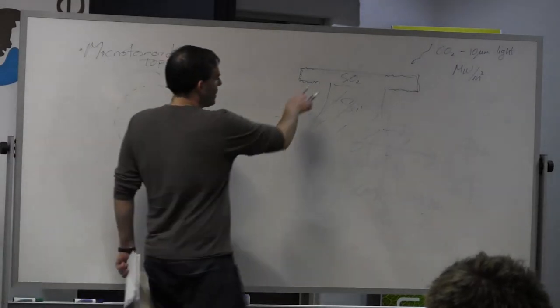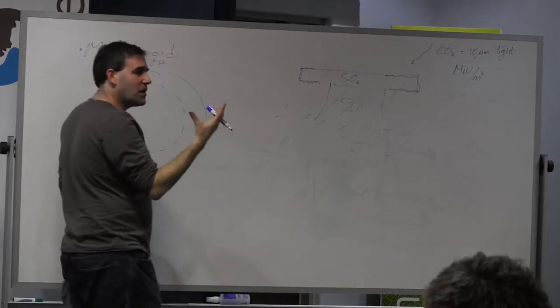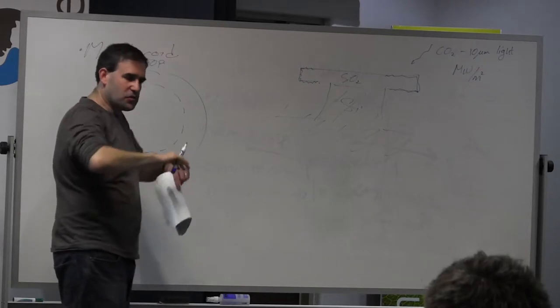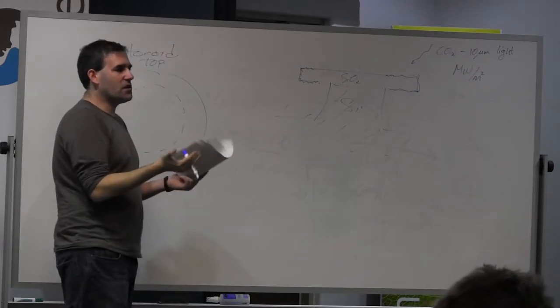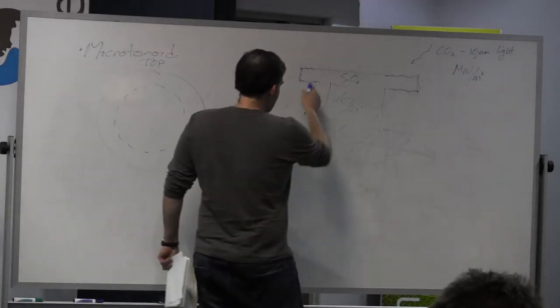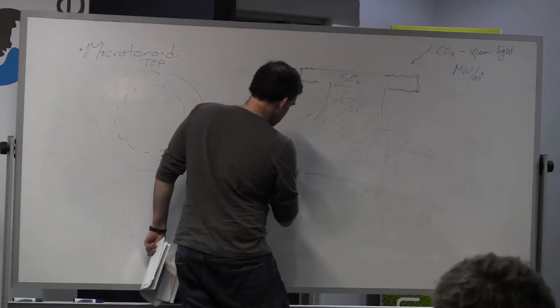Now what happens is essentially that this disk of stuff that you made melts right there sitting on the top of this mushroom. And it melts, and then surface tension just naturally causes it to develop really smooth surfaces and to bead up, so that after this 100 milliseconds, your microtoroid looks very smooth and lovely.